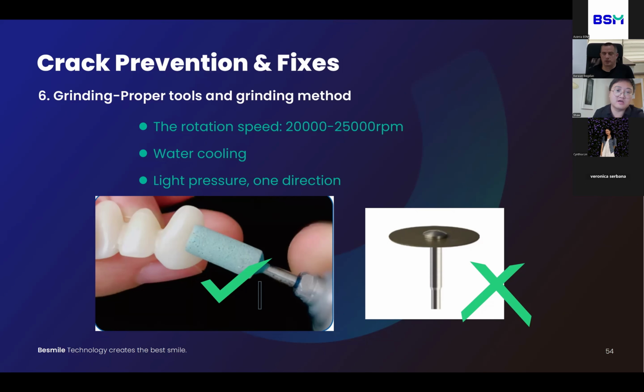And the rotation speed of the grinding machine we recommend is from 20,000 to 25,000 revolutions per minute. And the method to grind is one direction. One direction is better, with light pressure.